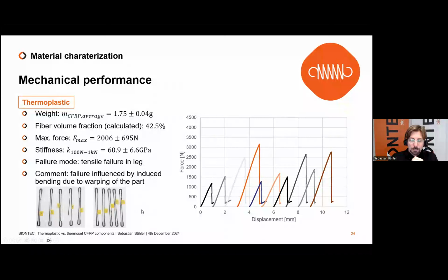And we saw another failure behavior of the material. We have the failure in the leg section, not in the loop, and with all 10 samples, we have the same failure mode. This is on the one side driven by the staple fibers, and on the other side a little bit by the warping of the part after the demolding.